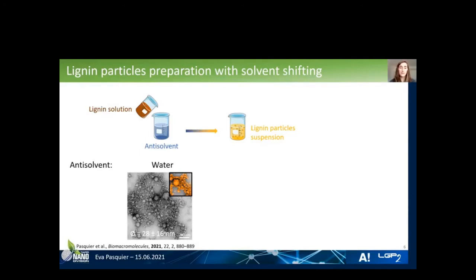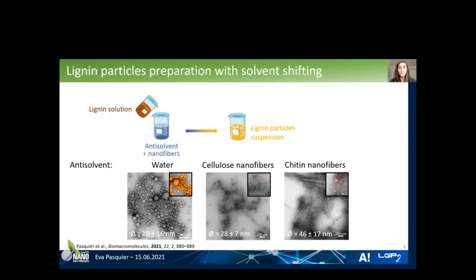Here you can see the TEM image of lignin particles that were made in water as an anti-solvent. You can see that they are round-shaped. The size dispersion is quite high. You can see very big particles. And also they are aggregated. So to change this morphology and also the size distribution, we added some nanofibers to the anti-solvent. And this led to lignin particles with smaller size distribution.